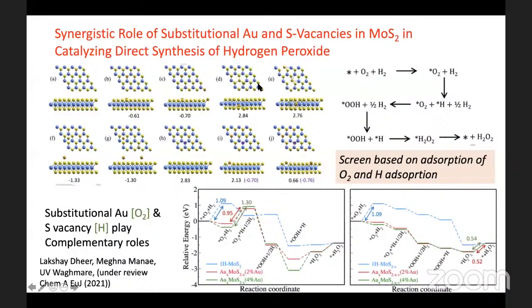So what we showed in this is we started with lots of configurations of MoS2 with gold and vacancies of sulfur, and then used screening based on adsorption of certain intermediates, specifically oxygen molecule and proton on these surfaces, and then selected only a few of them. We found that if you have a combination of substitutional gold and sulfur vacancy, they promote the rate limiting step, the barrier goes down. In fact, this is without sulfur vacancies, and this is with sulfur vacancies on the right. And you can see the barrier comes down and the reaction becomes absolutely smooth. So it's a totally computational prediction of a new catalyst for direct synthesis of hydrogen peroxide.